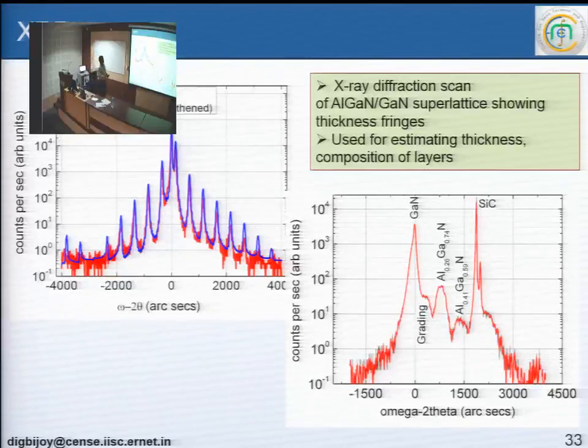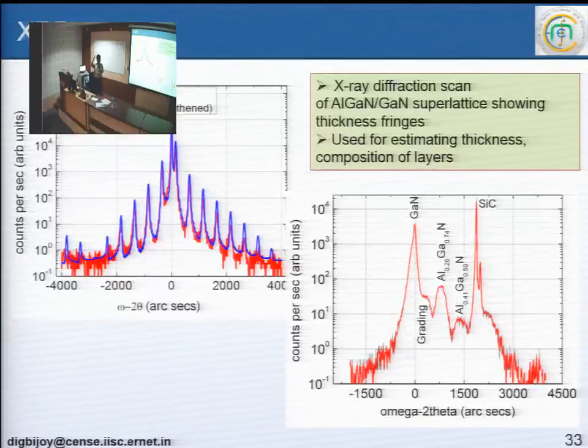So, for example, this is an XRD scan of a gallium nitride, aluminum gallium nitride superlattice. Superlattice means you have gallium nitride, aluminum gallium nitride, and you repeat the layers, say 10 times or 20 times: GaN, AlGaN, GaN, AlGaN kind of thing. These different peaks come because of the thickness fringes. Because you have different interfaces, your X-ray will diffract, right? So you have thickness fringes that come from the interfaces of the different layers. The red one is what the X-ray scan looks like, and blue is a simulation. You have dynamic simulation software with which you can fit the data, and from the fitting you can extract the period of the superlattice, the thickness of the different layers, composition, etc.